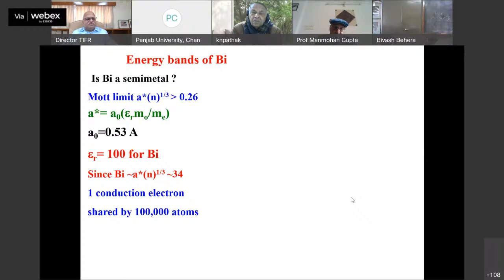Where A star is the effective Bohr radius, A naught is the Bohr radius, epsilon r is the dielectric constant, m naught is the effective mass, and me is the electron mass. So you plug the numbers for bismuth to see that this ratio A star is of the order of 34. So it is in the metallic range. But one unique thing about bismuth is that, as I said, since it occupies only 10 to the power of -5 of the Brillouin zone, one conduction electron is shared by 100,000 bismuth atoms. That's because of this low carrier concentration.